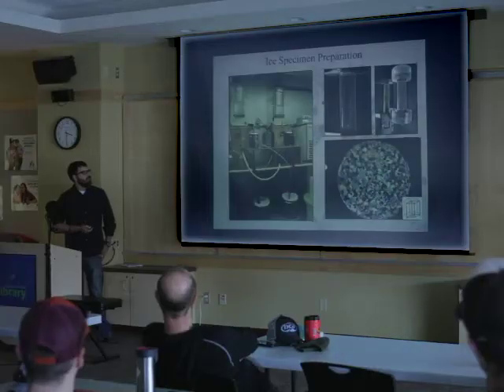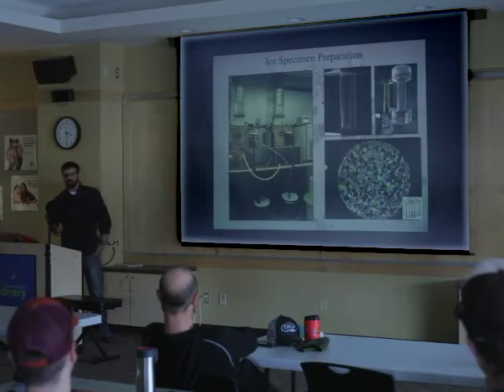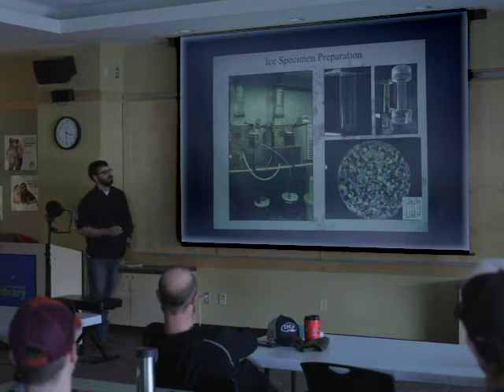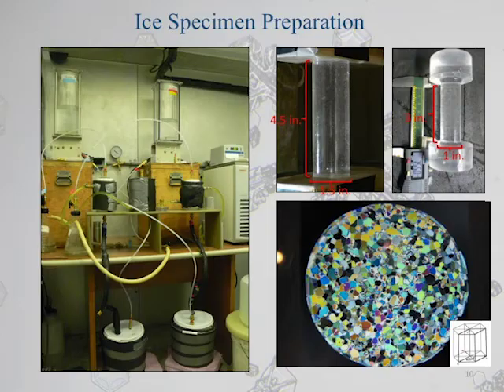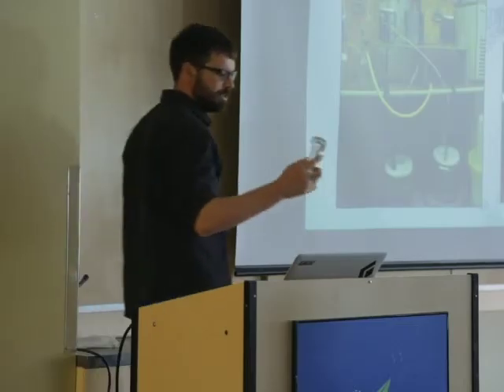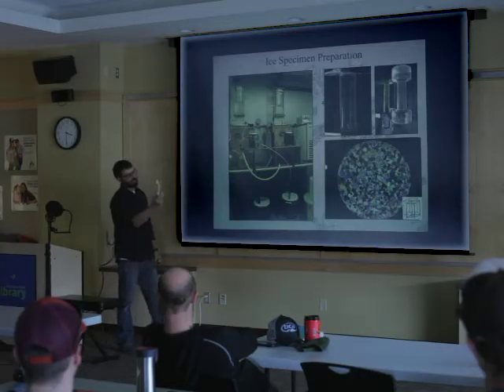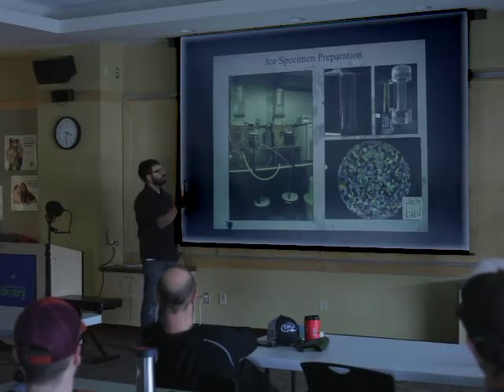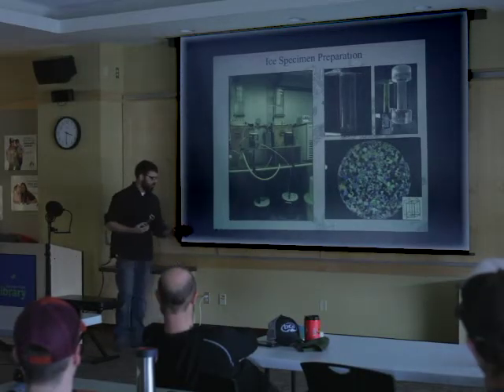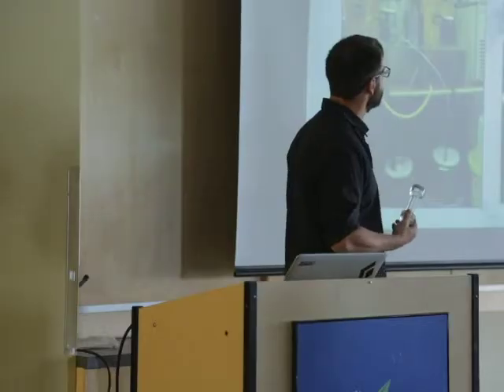So the objective behind this study, which was all laboratory-based, was to make samples of polycrystalline ice. Polycrystalline meaning that there's random orientation of grains in these samples, even though it looks pretty crystal clear. I have props. So this is what one of these samples looked like in real scale that we were making of polycrystalline ice. And if you look at its microstructure, you can see that it's polycrystalline.